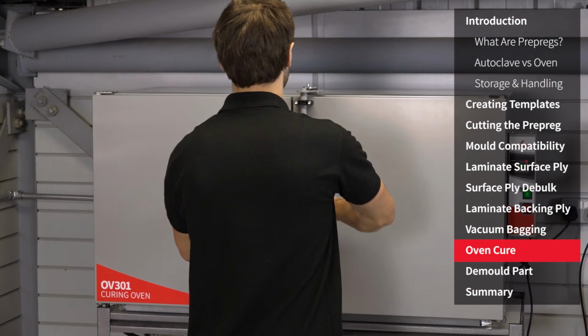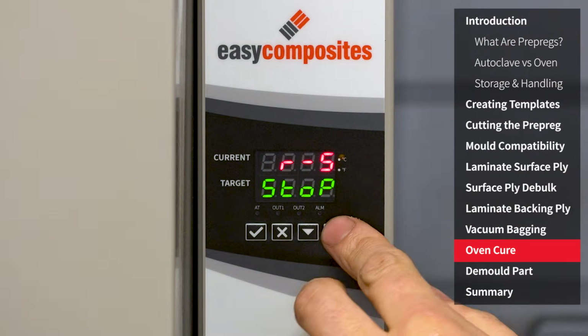The standard cure cycle consists of two stages. Firstly, we control the heating rate to an initial lower temperature and hold it there for optimum resin flow. And as you can see from the graph, we then increase the temperature to fully cure the resin and realise the material's full mechanical properties.